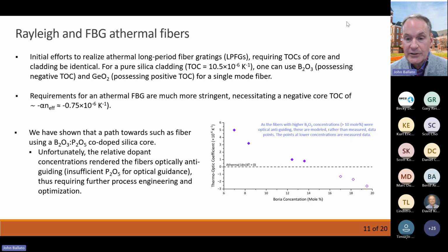Now, again, there are tricks to deal with that. You add more phosphorus and other things that raise the index. But in our measurements, we hadn't gotten far enough to do that yet. So those are anti-guiding fibers, which is where they're denoted as an open diamond as opposed to a closed, filled diamond. But nonetheless, the point is you can make these fibers. You have the additional considerations with respect to making them, index doping. But again, that's where we're going.